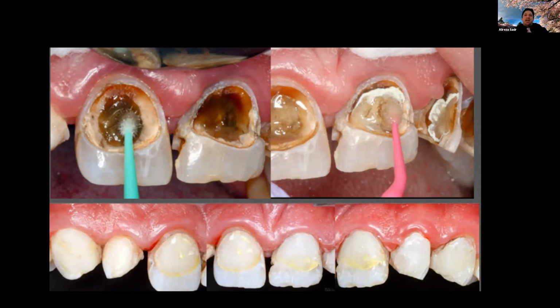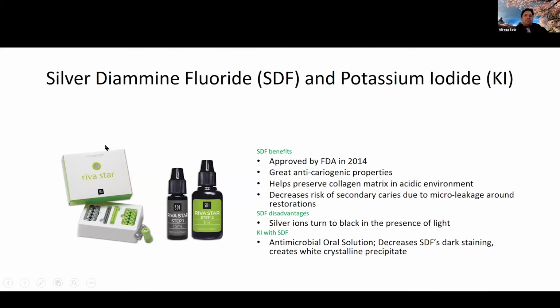And the reason is that the light curing of the material over SDF treated dentin increases the chance of discoloration. So if you can stay away from a material that needs light curing, you have reduced the chance of discoloration by a lot. And of course, use of potassium iodide is another way to do that. There is a product out there, Riva Star, where it will have its own antimicrobial effects, and it creates a white precipitate with SDF, so it will decrease the dark staining, and you can basically wash off that precipitate that is created with the potassium iodide and silver diamine fluoride.